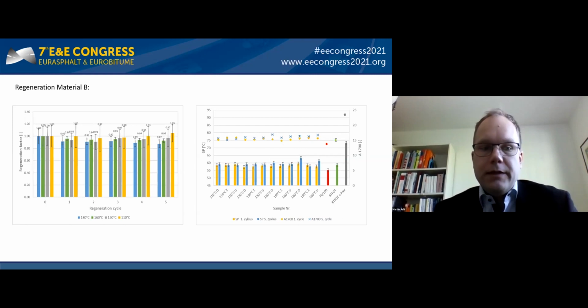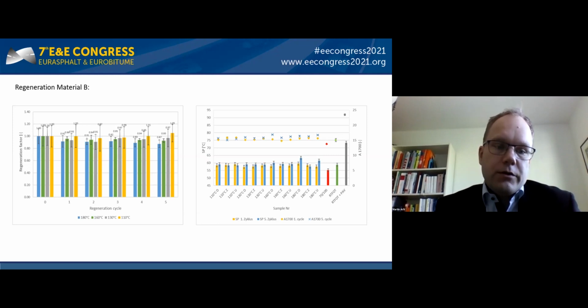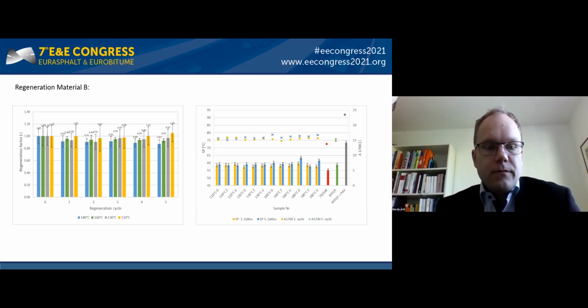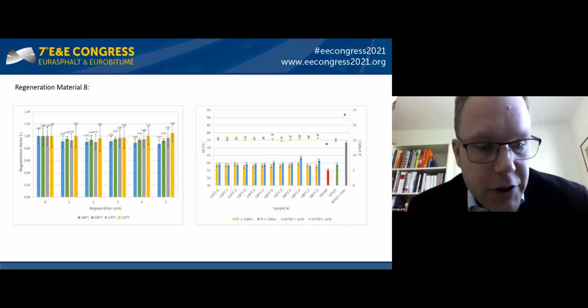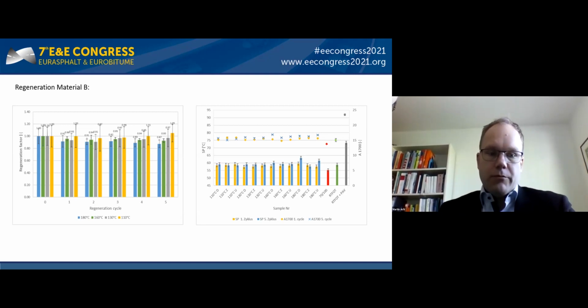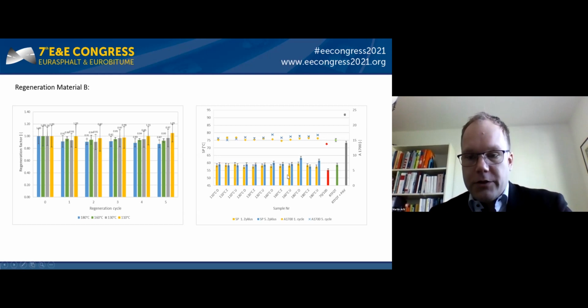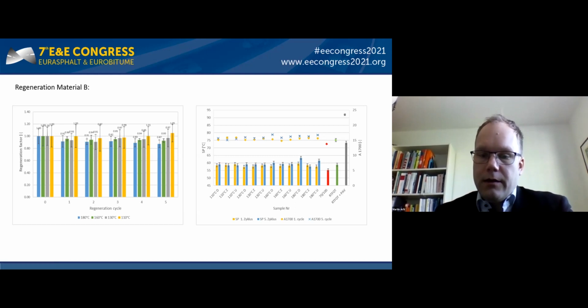The same you can see for material B, the wearing course material. There is also on the left-hand side picture the regeneration factor, which shows that the material is damaged in the first regeneration cycle by around 10%. So the maximum flexural strength is lowered and will not change much for all five following regeneration cycles. On the right-hand side picture, you can see again that the softening point, shown by the columns and the scale on the left-hand side, will not change much and not dramatically exceed the RTFOT short-term aging, the same as material A.